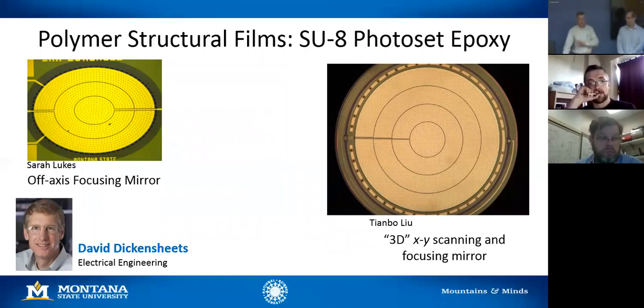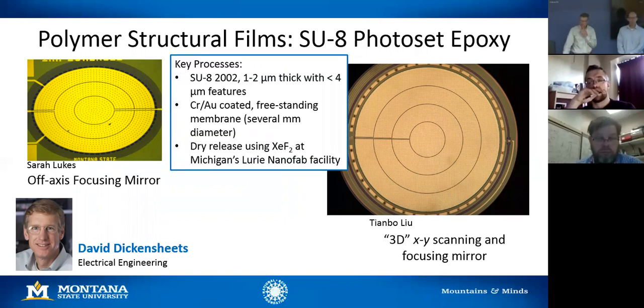So this is not microfluidics, but it's the same basic permanent epoxy, SU-8. On the left is an example of a mirror that Sarah Lukes, who's here, built. The key feature here is that this is a deformable mirror. It's a freestanding membrane of SU-8 that's several millimeters across, but the membrane itself is between 1 and 2 microns thick. We're using a material called SU-8 2002.